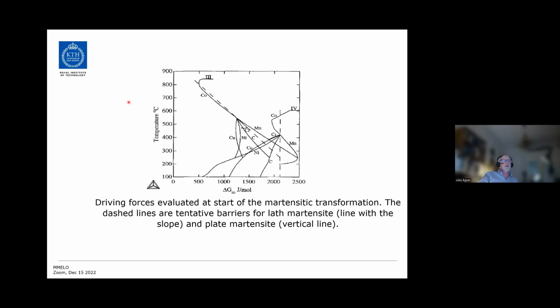So here is a diagram from the report. Here is temperature, and here is the driving force. And those are curves, solid curves for a large number of systems. But of course, there is some experimental scattering. So they concluded that this dashed line would be the barrier as a function of temperature for lath martensite. And for plate martensite, they suggested a constant value.